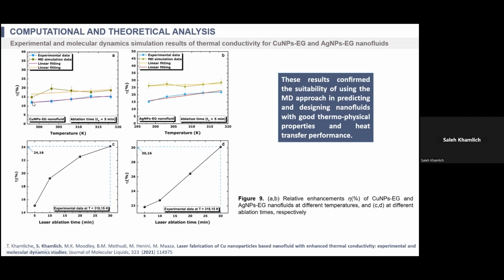So this is the experimental result of copper ethylene glycol nanofluid. This is the molecular dynamics again, and this is another one there, which shows you clearly that molecular dynamics allowed us really to come up with results which are comparable with the experimental ones. This means it's confirmed that the molecular dynamics approach is a suitable approach in order to design nanofluids. It can be used to design new types of nanofluids every day.